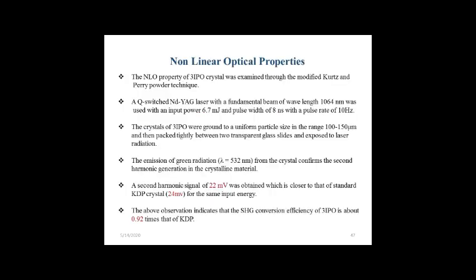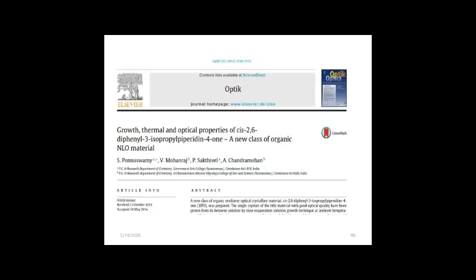Then another is non-linear optical properties. According to the harmonic signals, 22 millivolts was obtained, which is close to the standard KDP crystal's 24 millivolts, for the same input energy. The observation indicates that the SHG conversion efficiency is 0.92 times that of KDP. So this crystal is published in an optics journal.